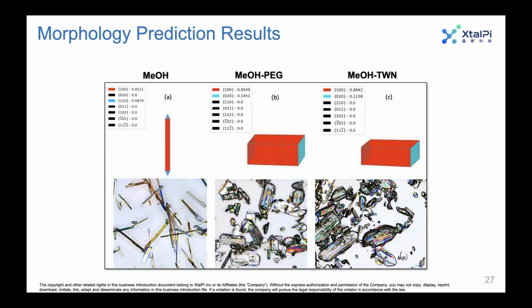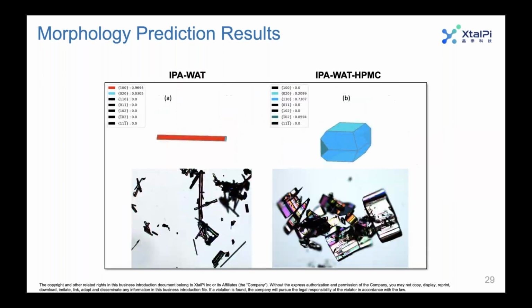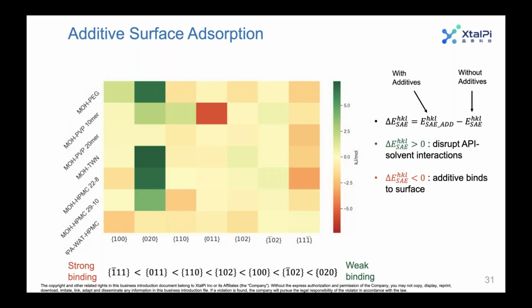So it was those real to virtual and virtual to real morphological phase transitions that allow us to change the morphology of metformin HCl so profoundly. And that's because the effect that the polymers have on the growth rate of those specific faces is profound enough that it can essentially switch those faces on and off, and the result is a totally different morphology. Whereas for the fast-growing faces, small changes in the growth rate or in the binding energy aren't enough to significantly change them morphologically. So what this tells us is that systems that might benefit from this type of additives are ones where there are faces that small changes in the growth rate can have a profound effect on the morphology. And the modeling that we've performed here can give you that type of insight.